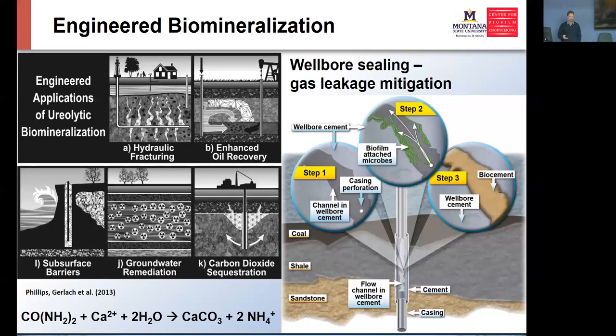So we're also working on engineering methods, and instead of struvite, we precipitate out calcium carbonate. Calcium carbonate happens to have several morphotypes, aragonite, calcite, vaterite, and so on and so forth. But the same mechanism is basically used by us. We hydrolyze urea and then precipitate out a mineral. And we use this for various purposes, mostly environmental remediation purposes. And we've done this a number of times in the field now, that we drill a little hole into the well to go into a channel, seed the channel with our microbes or the enzyme, and then fill it up with biocement through this process where we repeatedly inject urea and calcium.